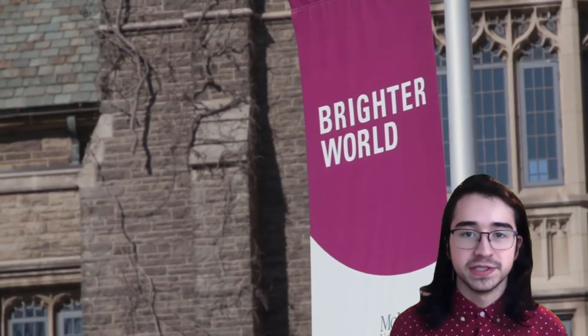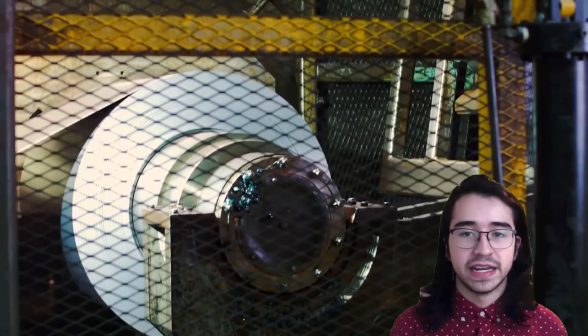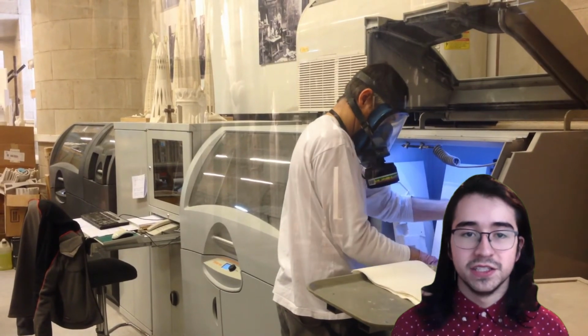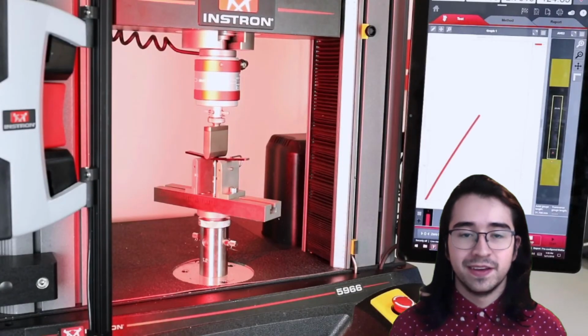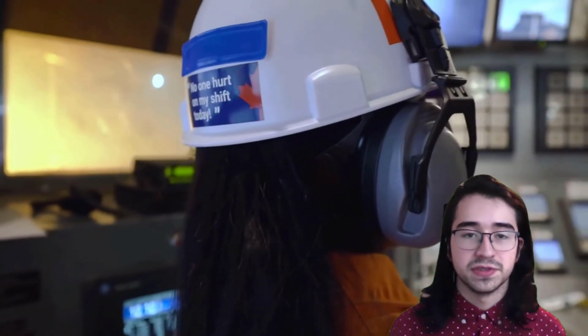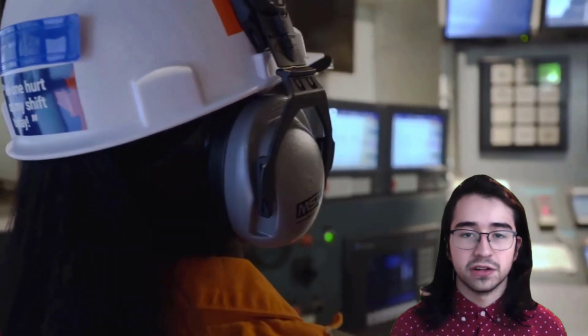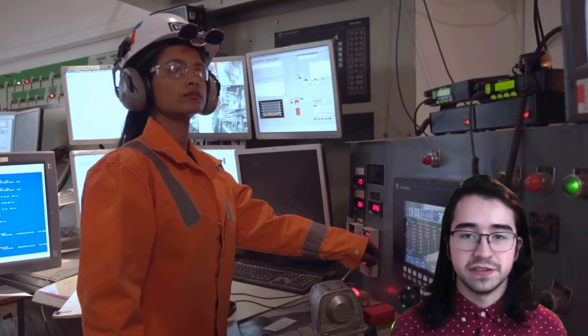For future Capstone groups, it's recommended that the group decrease the furnace temperature and coil speed in set increments and perform a design of experiments, or DOE, analysis on the bend test samples. Doing so will find the optimum temperature and speed to increase the bendability of the steel. It's recommended Stelco run the same project in a future date with a refined chemistry that will allow for further refining of the thermomechanical processing. This will permit the team to develop additional recommendations without substantially affecting throughput.